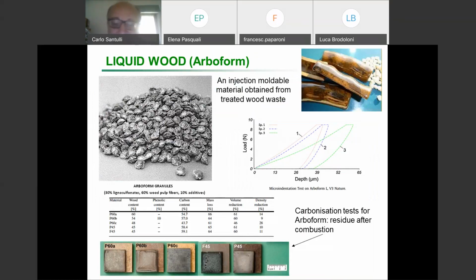Of course, it's a kind of living material. So in practical terms, you see this panel and they burn it. You burn it, and in the end, they wanted to demonstrate how much they were in the wood, and they wanted also to demonstrate that they were self-extinguishing. Because the problem with cellulose-based materials is that we started with materials which were self-combustible, not self-extinguishing. Nitrocellulose, which was one of the first plastics that was developed in the 19th century, was self-combusting.